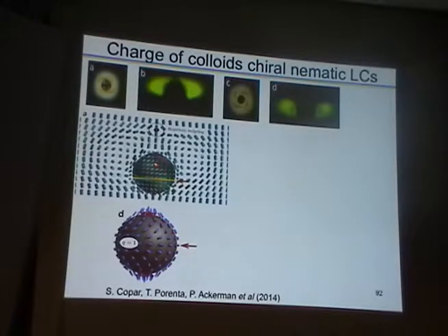It turns out that the colloidal particles in this case are accompanied by a loop of double twist cylinder, or double twist torus, and so they are essentially dressed by such a double twist torus, which appears asymmetrically with respect to the liquid crystal cell thickness. The particle is kind of pushed to one side, and the double twist torus is roughly in the middle of the cell, but then we have a hedgehog point defect, the hyperbolic point defect, on the other side.